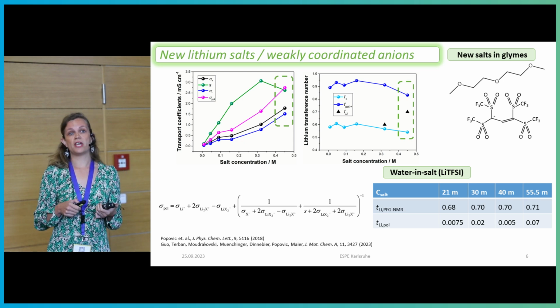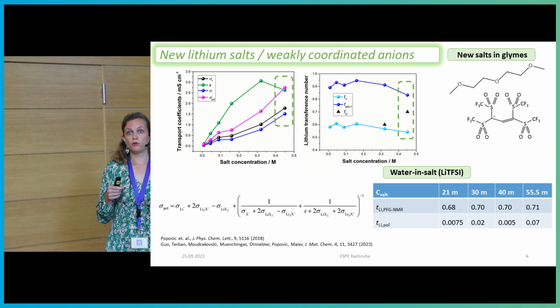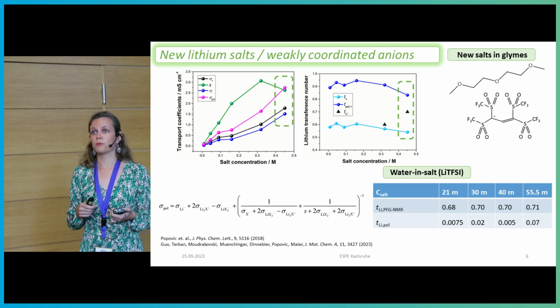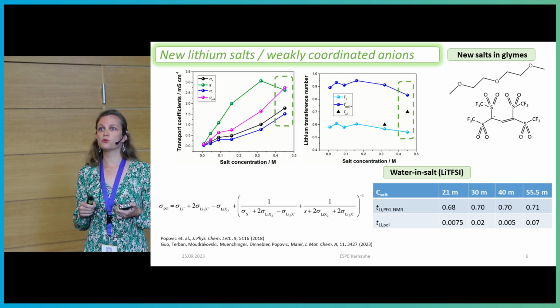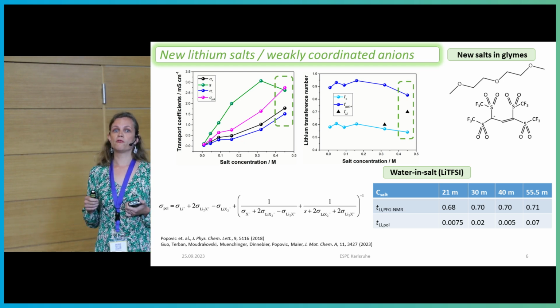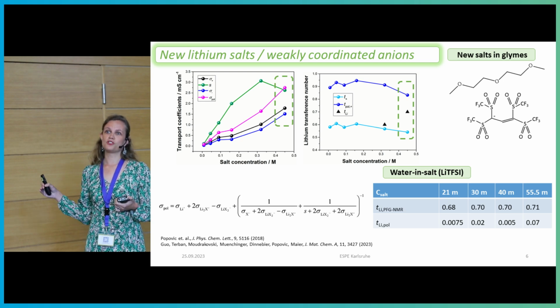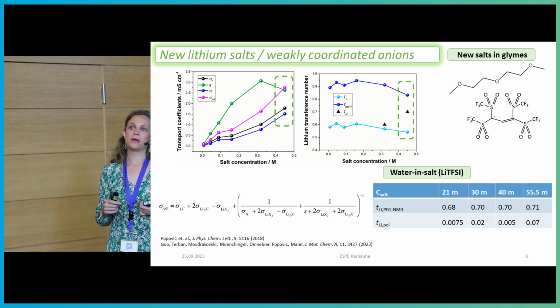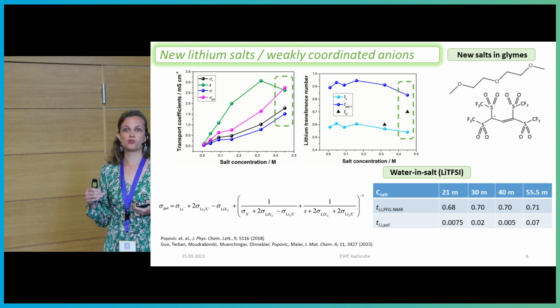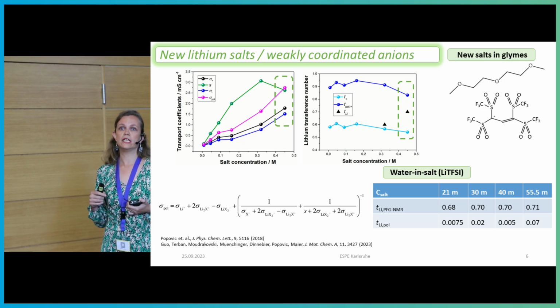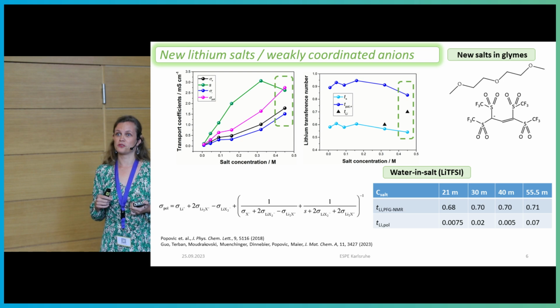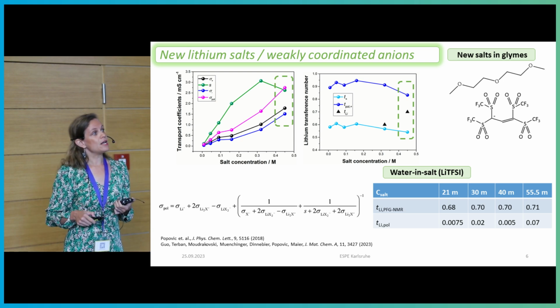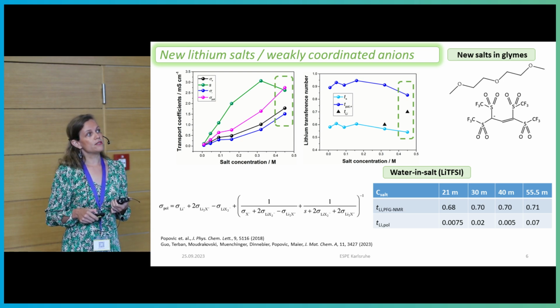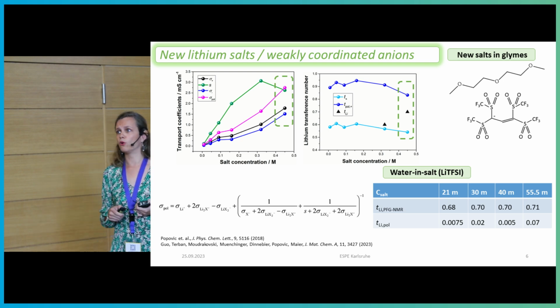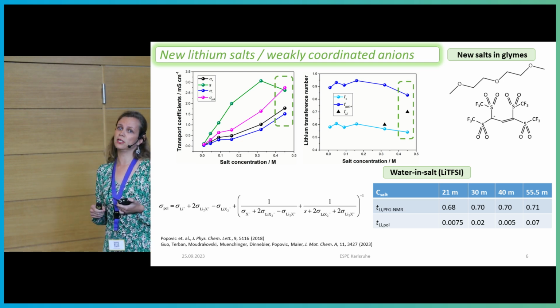These materials are highly reactive. So just to tell you that it's not easy to measure transference number electrochemically, and we used the trick of using lithium iron phosphate in its half-discharged form as electrode. So for the first time we showed that you do not have to use lithium metal to measure lithium transference numbers. But then we could measure that these lithium transference numbers are very, very low. So electrochemically, this is not a really great lithium transport material.